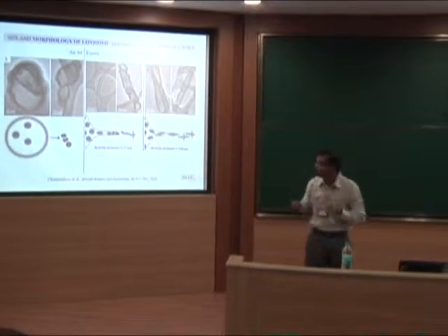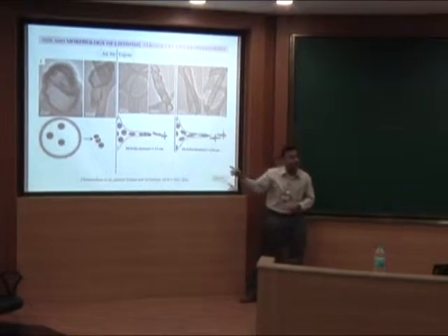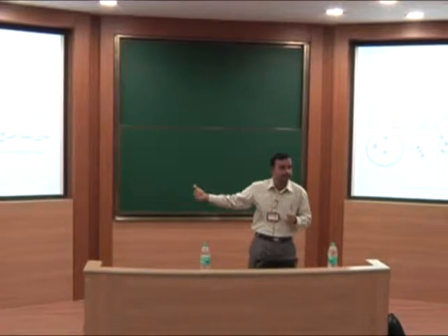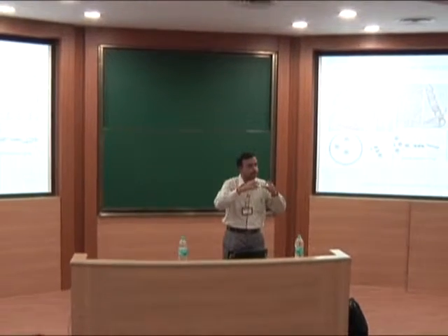The instrument which we are measuring with reports the mobility diameter, which takes into consideration the diameter of this particle. So when you report the diameter, which diameter? Is this the maximum dimension you are talking about? This diameter corresponds to 35 nanometer, and this diameter corresponds to 100 nanometer. The pathway of aggregation is head to tail like a chain in one case, giving 35 nanometer, and the other one is side by side. So this liposome gets distorted and forms a cylindrical structure.